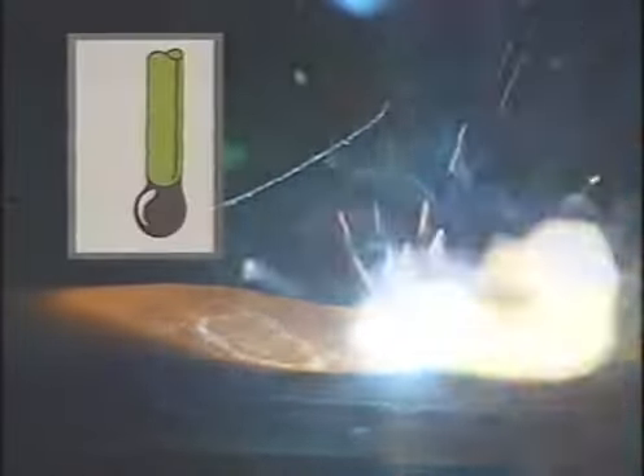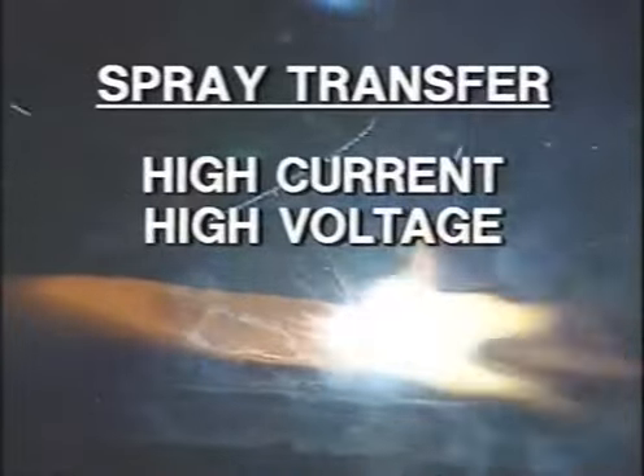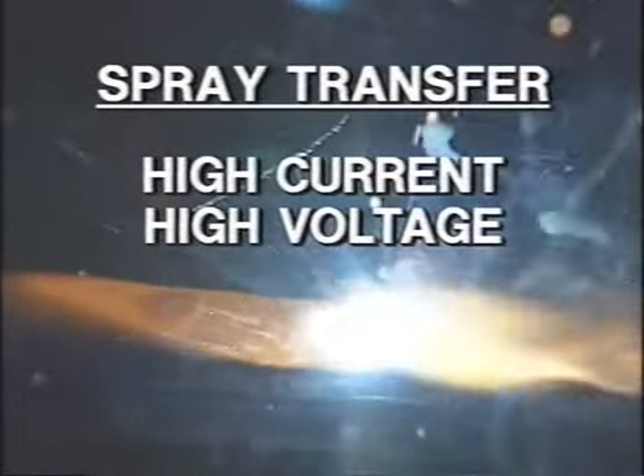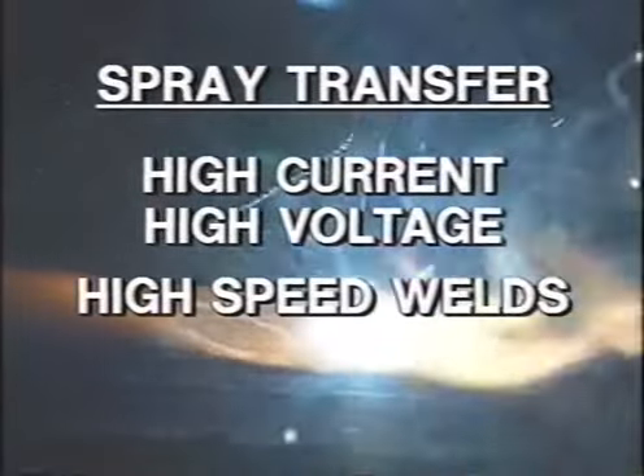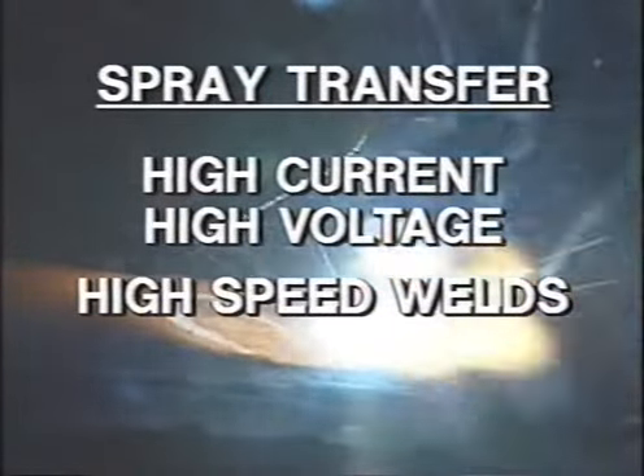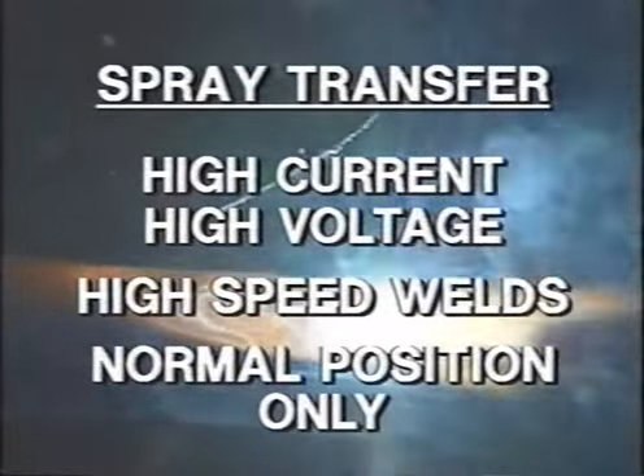When using the spray transfer method, fine particles of electrode wire are transferred rapidly across the arc to the weld pool. When using this method, high voltage and current are required. The spray transfer method allows high-speed welding and results in a good weld appearance, but welding out of normal position is not recommended.